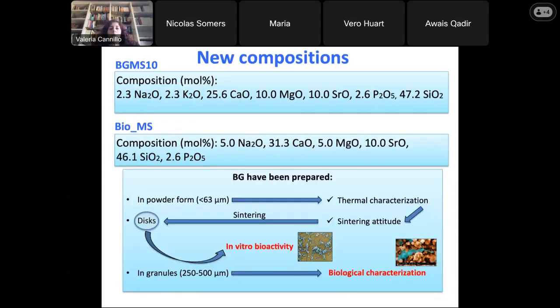Here, the two main compositions are reported. We worked on several different systems, but today I'm showing you only the two best ones. So you see that you have magnesium oxide and strontium oxide. The bioactive glasses have been prepared in different forms. First of all, in powder form for the thermal characterization by means of differential thermal analysis, DTA, and heating microscopy. And then they have also been produced in the form of discs by sintering to verify the sintering attitude and then verify the bioactivity and cell behavior.